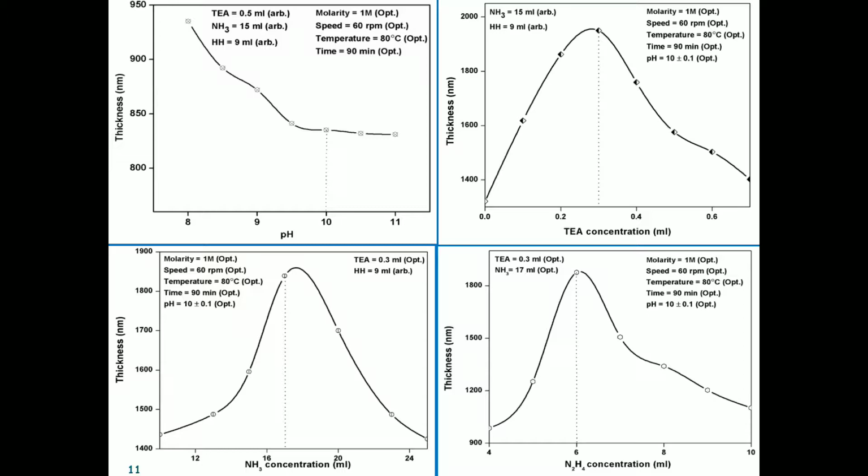The addition of OH ions with further increases in ammonia helps to make the Zn2+ TA complex more and more stable, that keeps the metal ions well arrested in the complex, thus decreasing the rate of release of metal ion species significantly, and hence the layer thickness decreased.